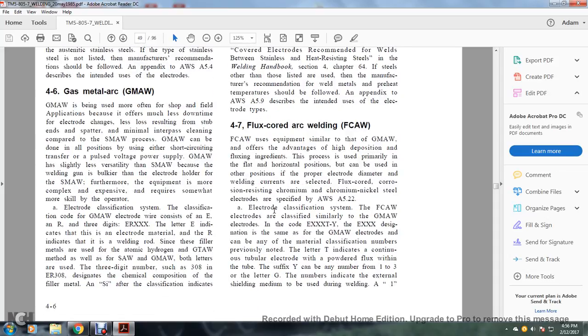4-7, flux cored arc welding. Flux cored arc welding equipment is similar to gas metal arc welding, and offers the advantage of high deposition rates, with fluxing ingredients to make sure the process is used primarily in the flat and horizontal positions, though it can be used in other positions. Proper electrode diameter and welding currents are selected. Flux cored corrosion-resistant chromium, nickel, steel electrodes are specified with the American Welding Society A5.22 electrode classification system.